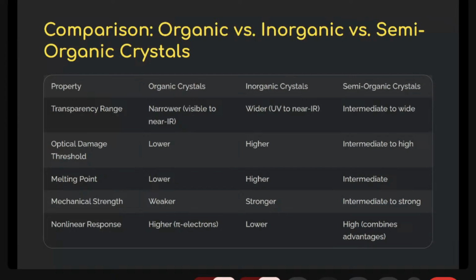The melting point is lower for the organic crystal, and for inorganic crystals it is much higher. The mechanical strength is weaker in organic crystals and stronger in inorganic crystals. But in case of non-linear response, organic crystals are higher and inorganic crystals are lower. So taking the advantages of organic crystals, nonlinear response, and of inorganic crystals, transparency range, optical damage threshold, melting point, and mechanical strength, we get semi-organic crystals, in which all the advantages of organic and inorganic crystals are present. So research on semi-organic crystals is far better than on organic and inorganic crystals.